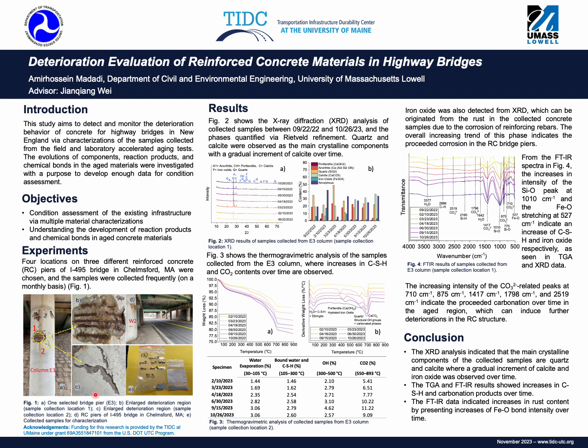For these samples, we collected them on a monthly frequency, and then the materials went through characterization by using X-ray diffraction or XRD, thermogravimetric analysis or TGA, and Fourier transform infrared spectroscopy. And the results are analyzed and shown here.